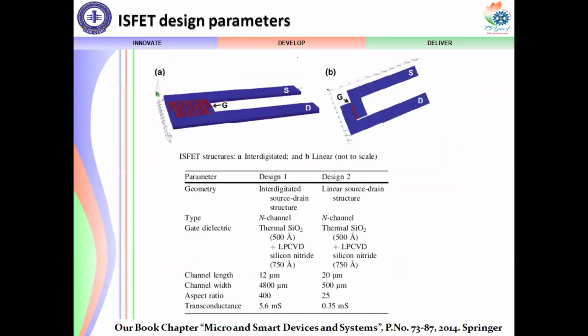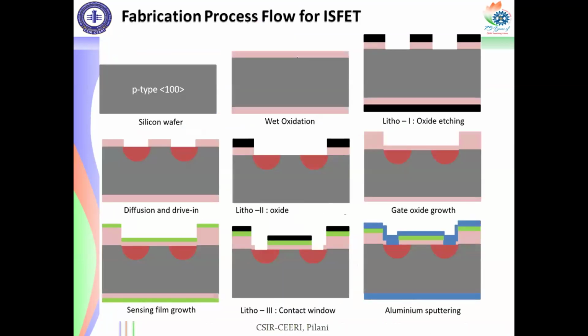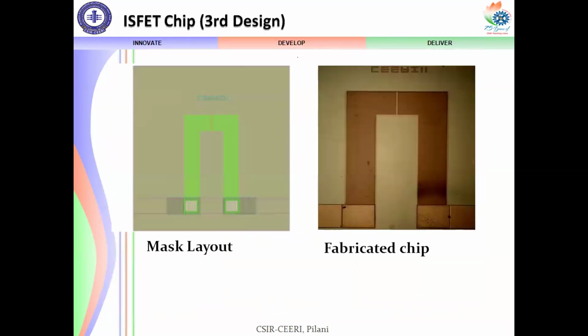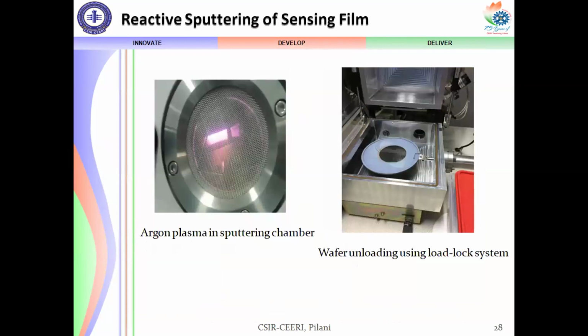These are some of the designs which we have used for the fabrication, meander shape, and as well as the planar one-dimensional structure. And this is the basic lithography method which we have used to realize it. This is the mask layout of the ISFET chip. On the right side is the gate of the ISFET. And we have worked on the reactive sputtering method to fabricate the titanium nitride and aluminum nitride film.